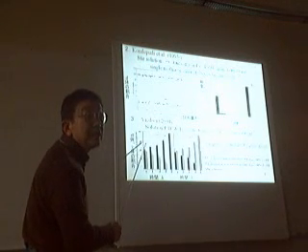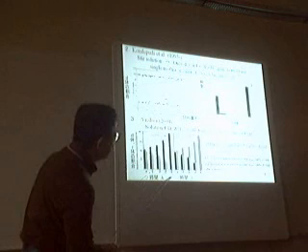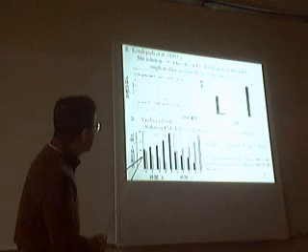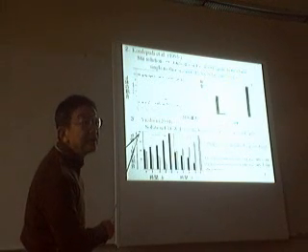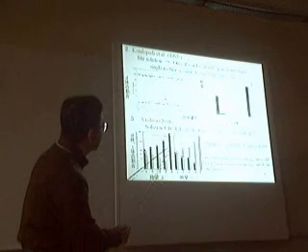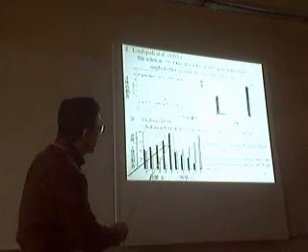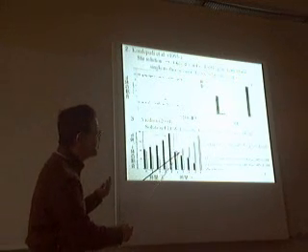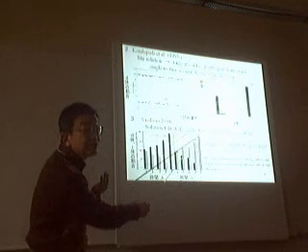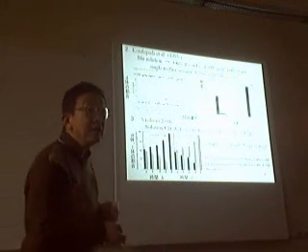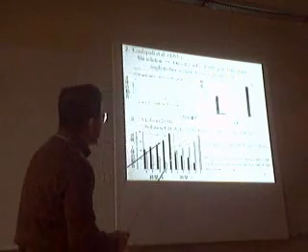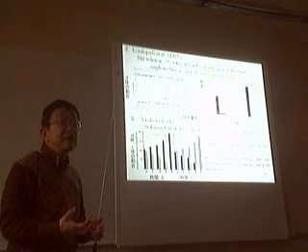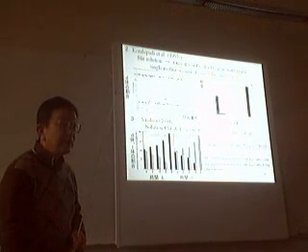And this is versus time of grinding. So 8 hours. Okay, and this is the concentrations. After 8 hours, every crystal turns out to be D type if D type is preferred initially. If L type is preferred initially, then everything turns out to be L type. And the excess has been added artificially in this case. From the beginning you have added L, or you get some other excess of D, yes. And then you start grinding the system.